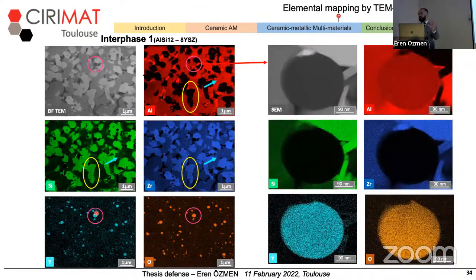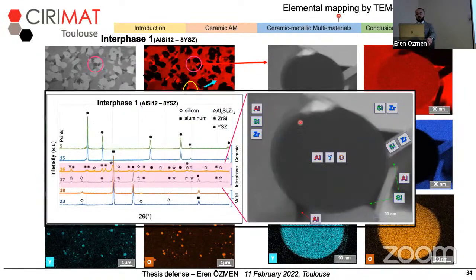So I increased the magnification again, and I specifically studied these dot-shaped areas. And what I see, these dots actually are aluminum, yttrium, and oxygen-rich areas where there is no silicon and zirconium. When I compare the existing elements with the phases that I detect in microdiffraction measurement, I see that for the first interface, the ternary phase is appearing in one area, the intermetallic phase is appearing in one area, and aluminum and silicon are appearing in different areas. However, no phases including aluminum, yttrium, and oxygen were shown in microdiffraction measurements.